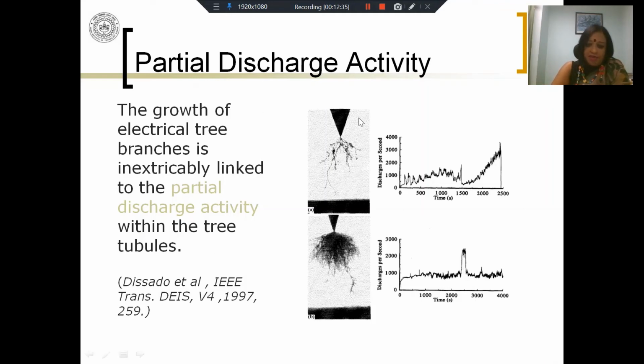So let's say here you have an example of the same tree at two different points of time. These pictures are taken from Dissado's paper of 1997, IEEE-DEIS. Here you see the tree has progressed to a certain extent, and then as you leave this energized, you see a lot of PD activity taking place. This gives you the discharges per second over a long period of time. Over 2500 seconds, you see considerable PD activity taking place.